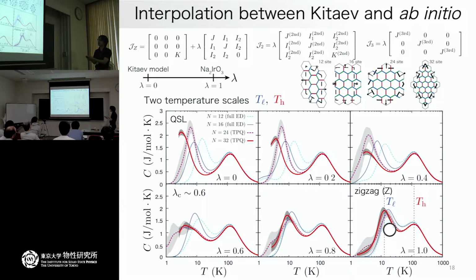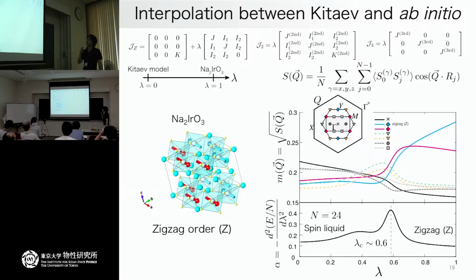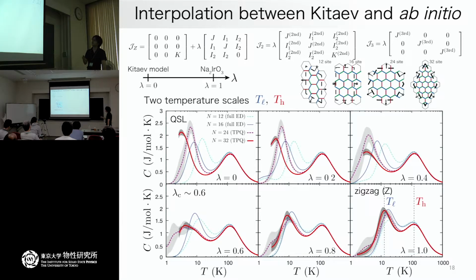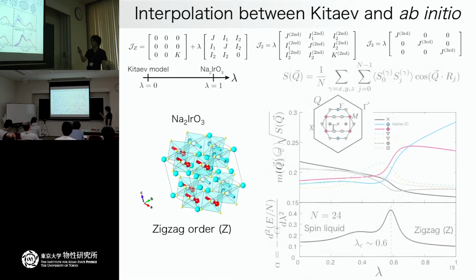In any case, we have a peak structure in the temperature dependence of the heat capacity. Here the horizontal axis is temperature in log scale, and the vertical axis is the heat capacity in units of joule per mole Kelvin. And here I show the result for the 12 to 32 spin clusters. For the ab initio model, we have good convergence with the system size, and the most severe finite size effect appears in this Kitaev limit. But anyway, in any case, we have a two-peak structure in the heat capacity.